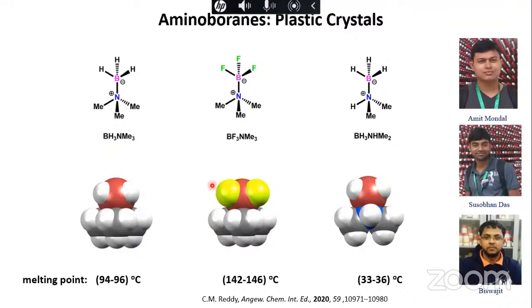And I'm going to show this particular example where we see a very clear difference between different molecules. For example, all these molecules have a globular shape. And in most of these cases where you see this plastic crystalline phase or disordered phase, you have more or less globular molecules, right? Here all the molecules have almost the same size or same kind of shape. But here you have 3 methyls, here you have 3 methyls, here 3 hydrogens, and then here you have 3 fluorine atoms, right?